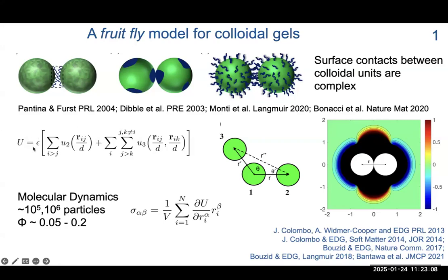So our interaction potential has this two-body part, and then it has a three-body term that effectively is a function that we've written in a way that is computationally convenient. But what it does is that when two particles come together, there is a resistance to do this type of motion. So I have here a little cartoon of two particles that are actually bound in this type of model within the attractive well. And the third particle will see this map, which represents the potential energy as it approaches these two particles that are already bound.